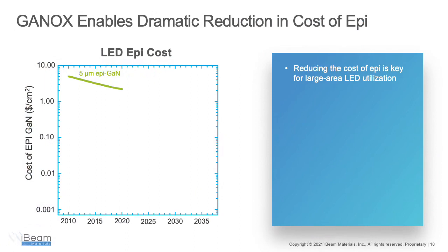As I said at the beginning, GaN epitaxy is expensive. The industry standard deposition process is metal organic chemical vapor deposition, or MOCVD, which is rather expensive. Current cost of 5-micron thick epi-GaN LEDs is about $2 to $3 per square centimeter. Here I plot on a log scale the cost of the epi LED materials. You see that there is plenty of room at the bottom as you compare to what I call the practical lower limit of materials costs.